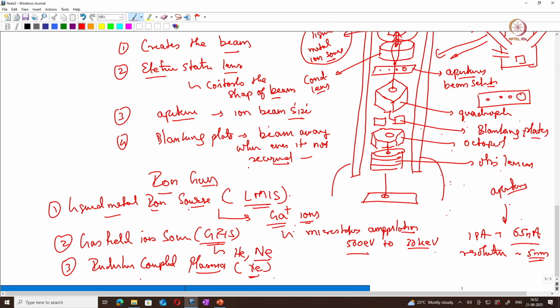Okay. So based on the time for milling, you can use these gas field ion sources or inductively coupled plasma sources, where the time for milling is much less, and you can mill samples on a millimeter scale with the plasma FIB sources. Correct. So with liquid metal ion sources, we can use gallium ions for a few microns, and the resolution is 5 nanometers. But for the gas field and plasma sources, the resolution is much lower, so it can be a few hundreds of nanometers. But the rate of milling is much higher for these sources.